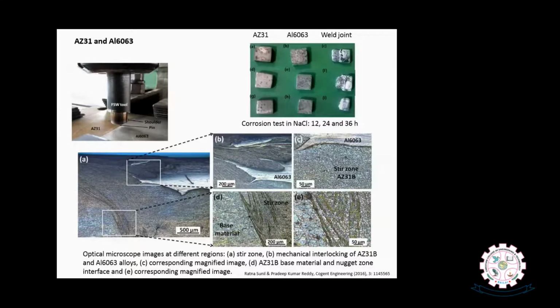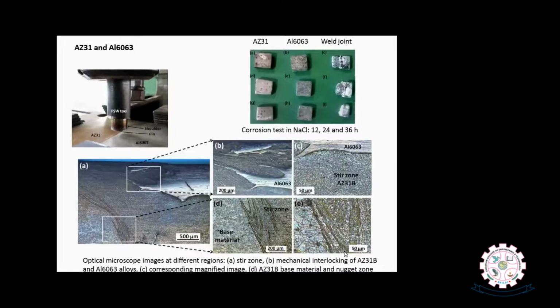Magnesium usually acts as an anode when it is coupled with other metals, and the other material, maybe steel, aluminum or copper, usually having higher corrosion potential, acts as the cathode, and a galvanic couple is established between the magnesium and its counterpart. Therefore, magnesium will be gradually degraded. So joining dissimilar metals may have an ill effect on the corrosion performance of magnesium. If during the application the structures come into contact with a corroding environment, special care must be taken to avoid the corrosion problem of magnesium.